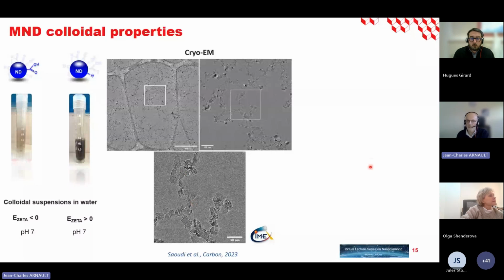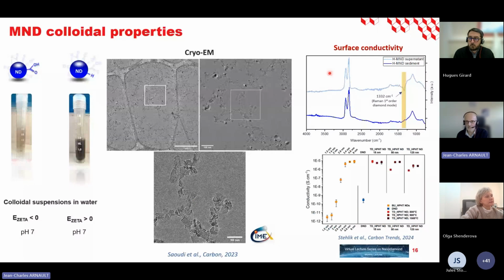Another interesting property, and I will come back to the IR spectra, is related to a surface conductivity. So this curve compares milled hydrogenated nanodiamonds in the sediments and in the supernatant. On the top, particles stable in water, on the bottom, the sediments. And you can see that if you compare the spectra in detail, you see here a specific feature that is really related to the particles able to be suspended in water. And the position corresponds to the Raman first-order diamond mode. So this was observed by several groups, including ours, and it has been attributed to a Fano effect and to destructive interference, and related to a surface conductivity on their surface.